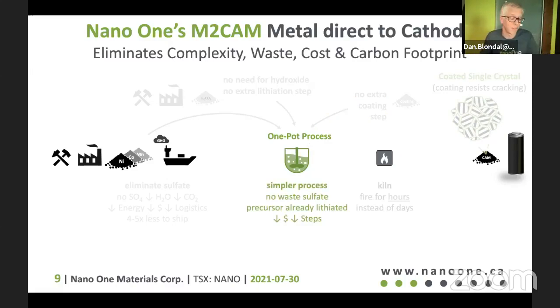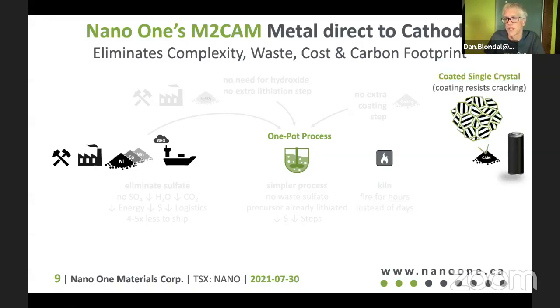And the precursor already has the lithium and the coating material in it. So there's fewer steps and, of course, reduced cost. That chemical process in the one pot process produces a mixed compound, a composite material that fires readily in the kiln. So it doesn't take as long because everything's actually already chemically mixed together. So we're firing in that kiln for hours instead of days for reduced cost. And ultimately that produces the single crystal coated materials that we looked at in the video for increased durability.